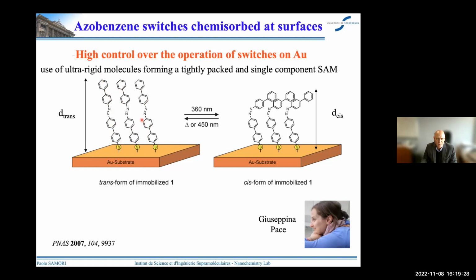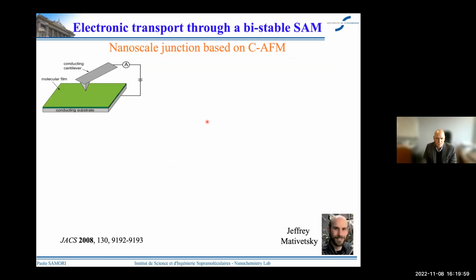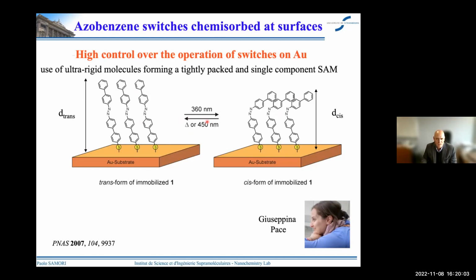which can undergo isomerization from the trans to the cis form with a very high yield, due to the tightness of the packing and the crosstalk between adjacent molecules. The cis form in this kind of self-assembled monolayer is more stable than in solution thanks to the presence of pi-pi stacking between adjacent molecules. And then one can trigger the back isomerization to the trans either thermally or with visible light. This kind of isomerization has been observed by scanning tunneling microscopy on the molecular scale. I have no time to present this, which was discussed in this PNAS paper. We observed a pretty large domain of several hundreds of nanometers that can be switched with UV and visible light stimuli.